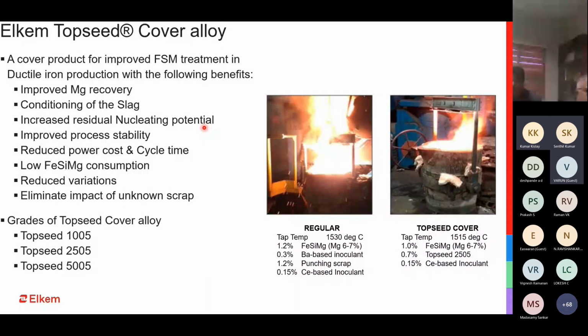I'm talking about additions to the inoculation. The other way of doing it is by having a very good treatment cover. So when you're producing ductile iron, we all know that we have punching scraps, or sometimes even turning borings or other such things which we add as a cover. The role of the cover in these cases is to delay the magnesium reaction. What do we want to achieve? We want the magnesium reaction to happen when you have a sufficient amount of metal in your ladle, so that you get a better recovery of magnesium.